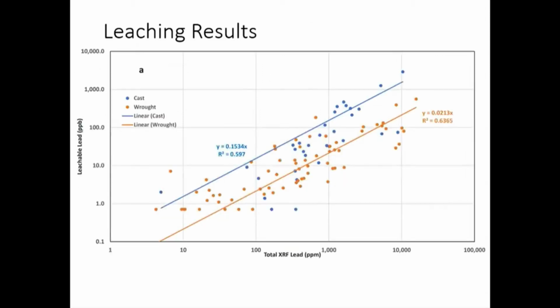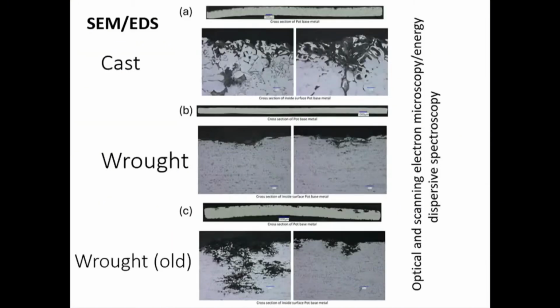Now, if you separate the wrought pots and the cast pots, you start to see some dramatic differences, right? The wrought pots tend to leach less lead than the cast pots, which is an important finding. And you can see my correlation coefficient at least went up to something a little higher, which was nice. Okay, so there's this story here.